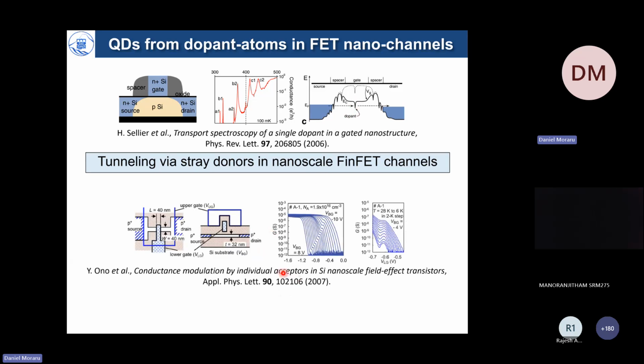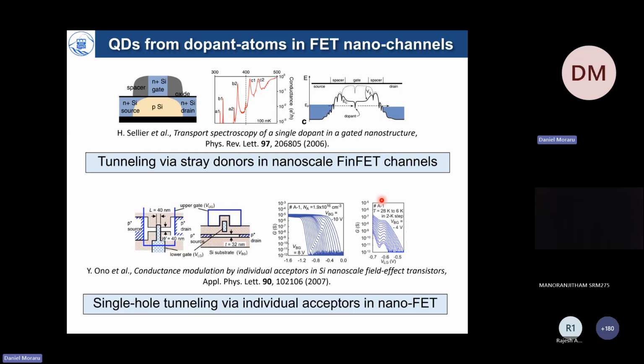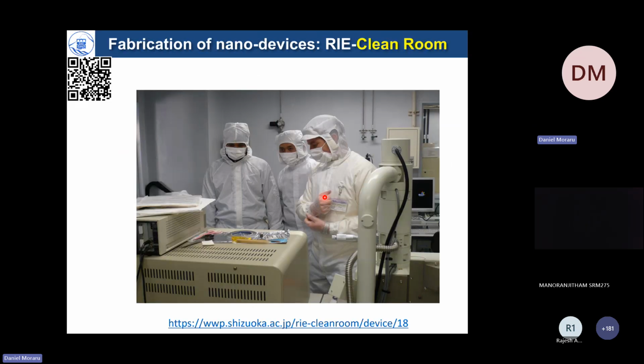Later on, we could also demonstrate individual acceptors showing similar modulations of the conductance in a p-type transistor. As you can see, the transistor switches on by applying a more negative gate voltage, but it also shows a current peak on the side. This all happens at low temperatures, but it shows that single dopants, either donors or acceptors, can modulate the current significantly. Now, what we do in our lab, and you have a QR code here for our clean room, is to utilize the clean room facilities at our institute and fabricate the nano devices ourselves.